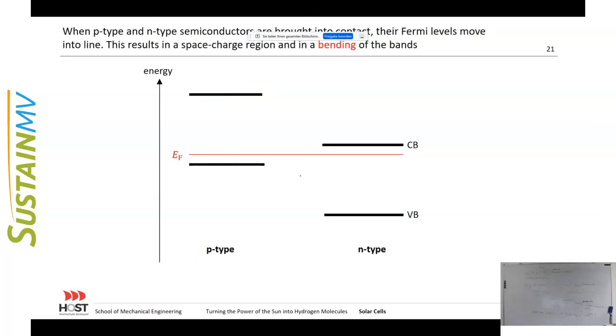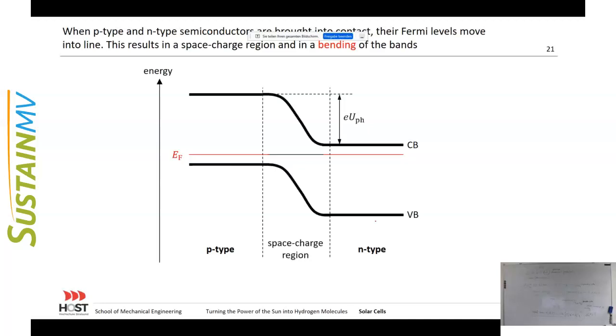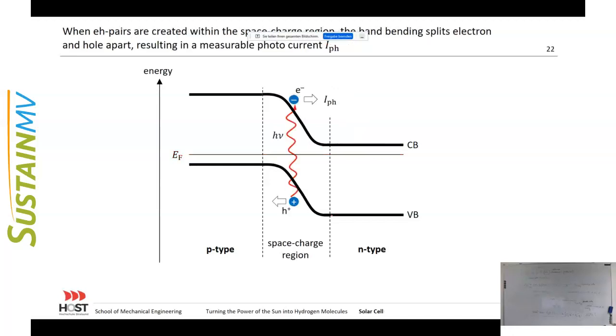If we now bring both P-type and N-type into contact, then for very principal reasons, the electrochemical potential, the Fermi level, becomes equal. The Fermi level is now in line, left in the P-type and right in the N-type. This leads to a bending of the conduction band and the valence band, so they look like a slope. If we now create by means of a photon an electron-hole pair, just as before, then due to the band bending the electron and the hole are split apart. The hole moves to the left and the electron moves to the right. In this case we can measure an external photocurrent. And these are the electrons that we need for splitting water into hydrogen.